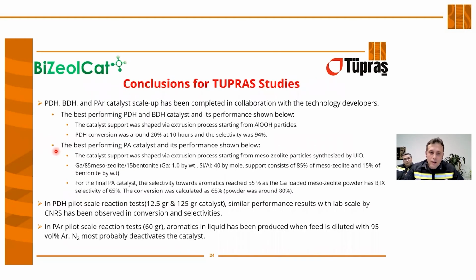As a conclusion, the propane dehydrogenation and propane aromatization catalyst scale-up has been completed in collaboration with the technology developers. Here you see the best performing propane dehydrogenation catalyst and its performance, considering that the catalyst support was shaped via an extrusion process, starting from aluminum oxyhydroxide particles.